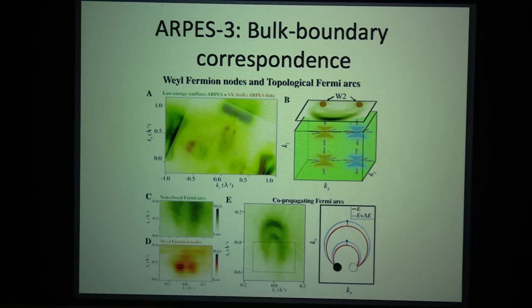Now we broke the crystal symmetry. If you restore that center of symmetry, then the Weyl points will merge into each other. They will become a Dirac semimetal, right? Then you can see that the arc will become a loop, so it's not an arc anymore. So then that topological property is gone. It may be stable if there is some additional symmetry. If there is no additional crystalline symmetry, then those closed loops will collapse. They're not stable.